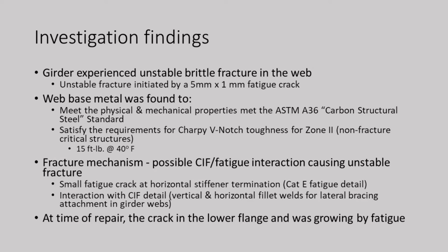We're looking at this crack that's very small, and we really don't believe that on its own it started such a big brittle fracture. It had to have some help. So maybe the constraint-induced fatigue, CIF: we had constraint in that area, and maybe that helped promote the brittle behavior of the steel and gave us what we got. We're not sure. But anyway, we got this category E detail that says fatigue, and we got the type of detail and the fact that the fillet welds touch each other. So it could be CIF as well, or it could be an interplay of those two.